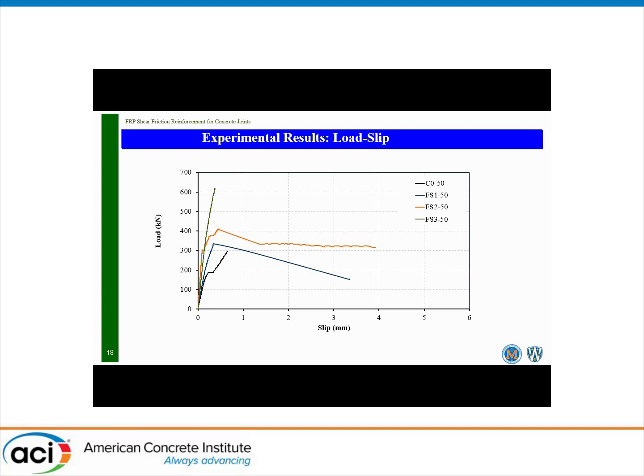Adding 1 FRP stirrup, 2 FRP stirrups, 3 FRP stirrups, the behavior keeps improving in terms of ultimate load carried and post-peak performance. For 1 FRP stirrup, it enhances the pre-cracking stiffness a lot and the ultimate load a little bit, but after a physical crack developed at the interface, 1 FRP stirrup was not enough to resist that amount of shear, and the specimen failed suddenly.